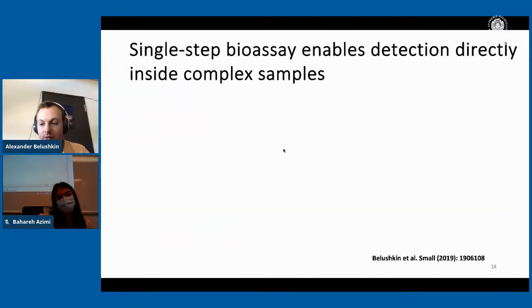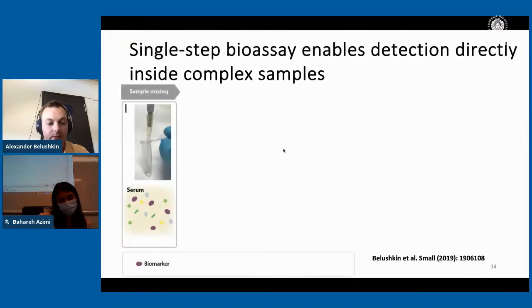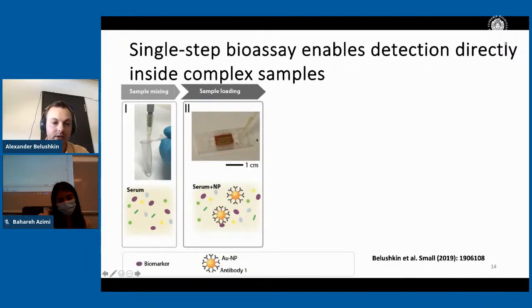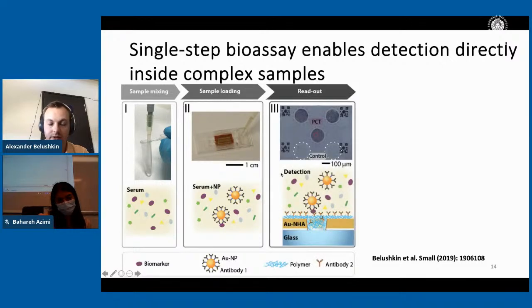The next step was to enable in-field use with a single-step bioassay. We wanted to have it as simple as possible so that we can perform tests outside of the lab. The way the assay works, we take the nanoparticles and put them directly into the serum sample. Then this whole mixture is loaded on the chip where the nanoparticles can bind on the surface of the nanoholes. Then we stick it into the reader, and this is the kind of readout that we typically see: 3 spots with the antigen of interest and 2 negative controls.